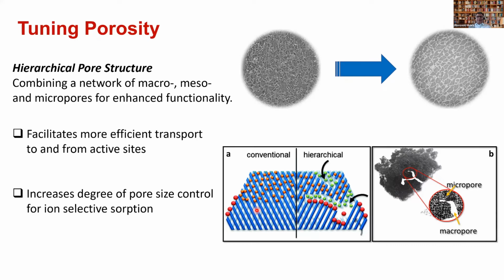flow properties. So basically, combining a network of macro, meso, and micropores enhances functionality because it facilitates more efficient transfer to and from active sites, and also increases the degree of pore size control for ion selective absorption. And these are our own images. You start from biomass and you have this biochar.